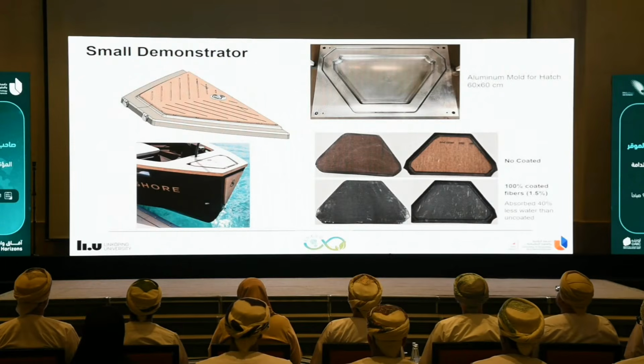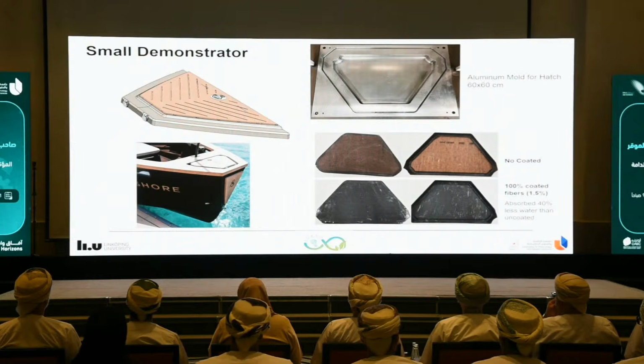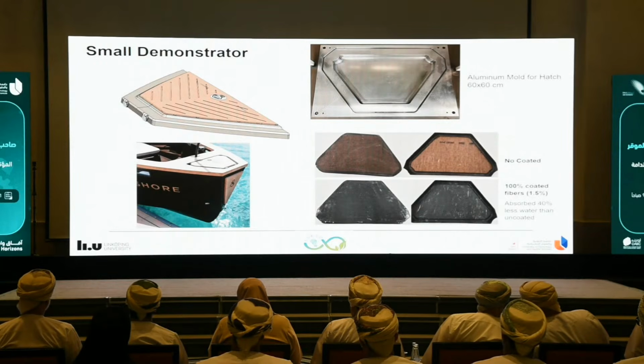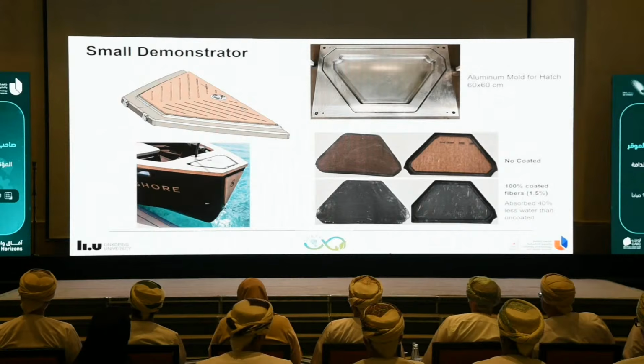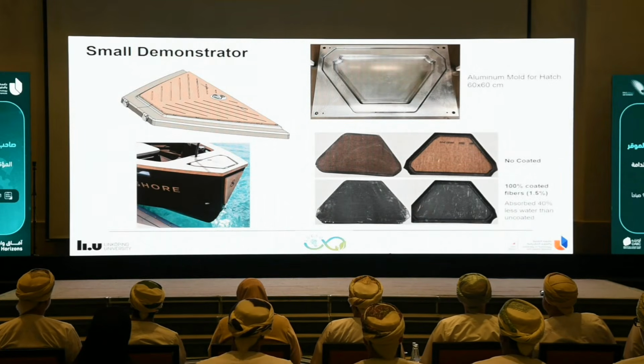So we made this part in the lab. The top part is the boat. We used a metallic mold, and we made it using vacuum infusion. What you see on the top is the uncoated part. What you see on the bottom side is the fully coated part. And we put them in water also for 1 month, and we observed that the coated fibers absorb 40% less water than the uncoated one. So this is something that we have analyzed.